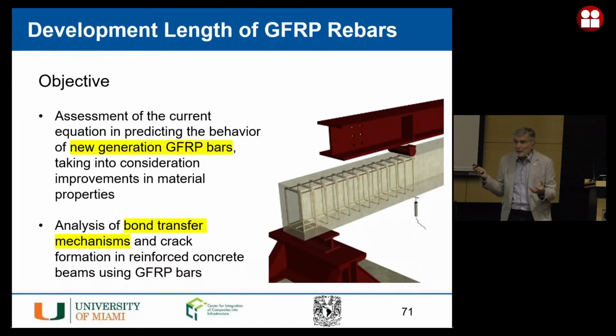steel. Well, in FRP, if you have a bar that, for example, provides you bond because of sand coating, well, the particles of sand will remain stuck to the concrete, and it's almost like, if I were to give you an image, the orange peel. Okay, it's like the peel remains stuck to the concrete and the orange comes out. So because of this, you have less bond. And even if you have ribs made out of FRP, the stiffness is actually much less in the ribs because they are resin rich. So it's almost the same stiffness of the concrete. So you eventually can break, actually you typically break the ribs.